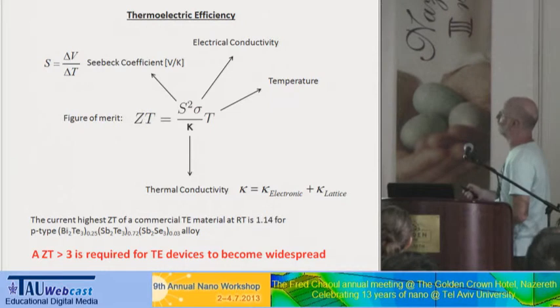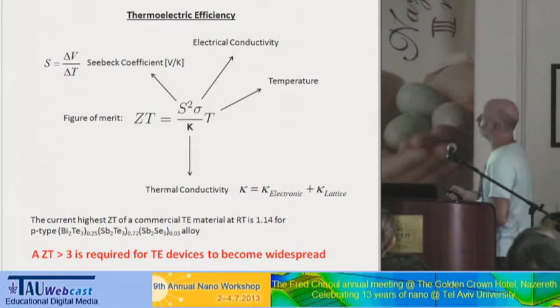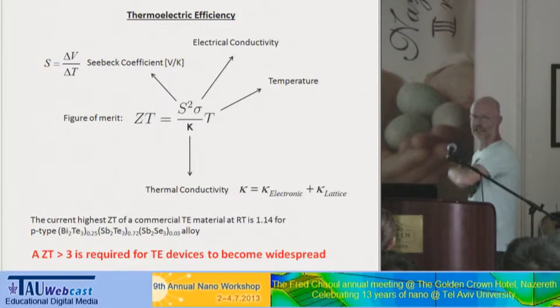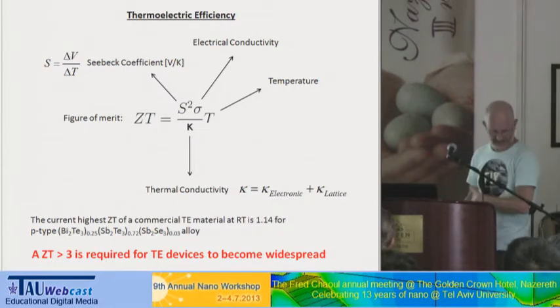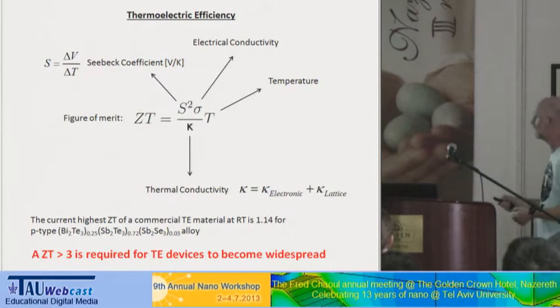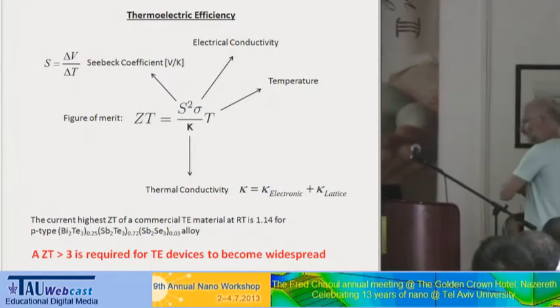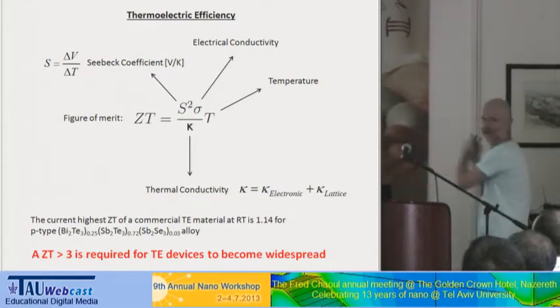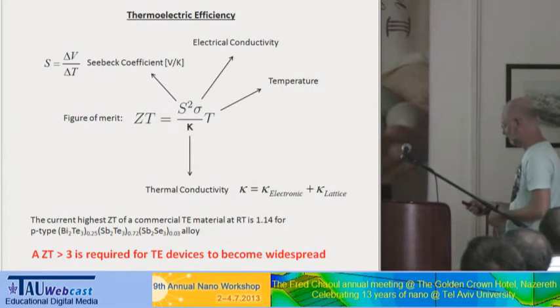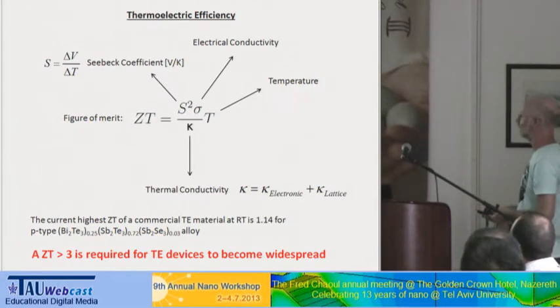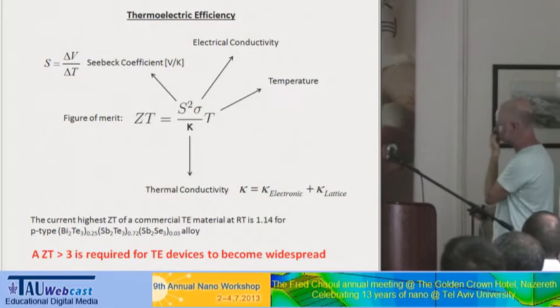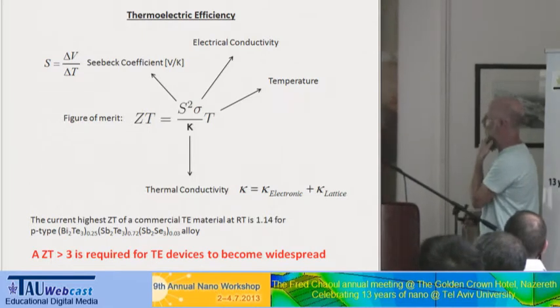The other thing that you need to worry about if you want efficient thermoelectric materials is that you should have high electrical conductivity. And you need to make sure that the thermal conductivity is as minimal as possible, because then you make sure that if you take heat from one side to the other, it won't go back. The thermal conductivity has 2 components, the electronic thermal conductivity and the lattice thermal conductivity. You need this to be as minimal as possible.